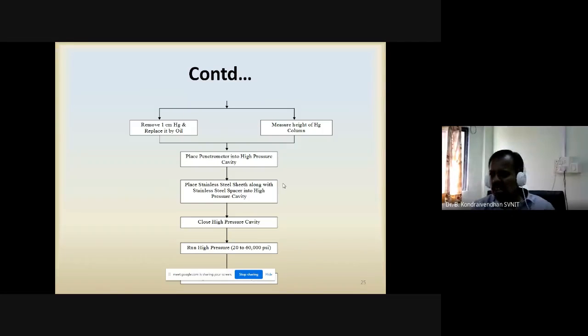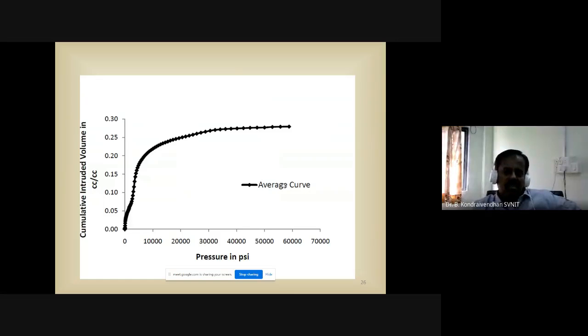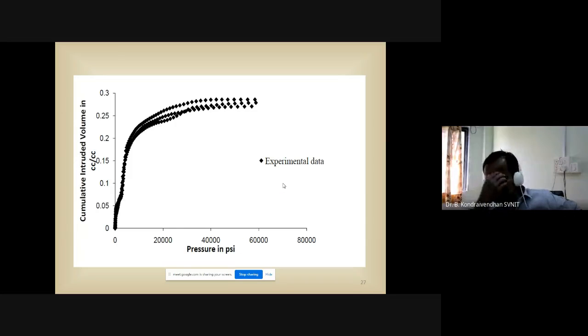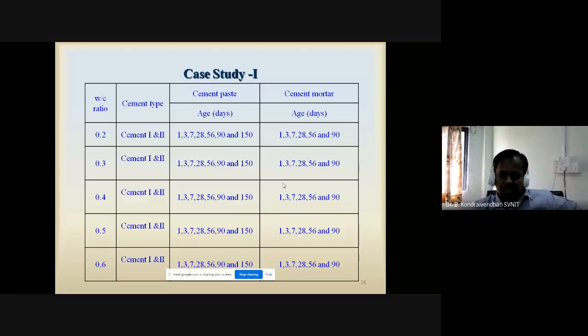So generally it takes around 1.5 hours for one sample, but for every mix we have to do at least 3 samples. Then we have to take the average. Okay, so this is the average cumulative intruded volume versus pressure curve. This is done up to 60,000 psi, and we have to do 3 samples and finally take the average also. Taking the average curve is also not so easy. Further, you have to use some software. Okay, so that's how we got it.